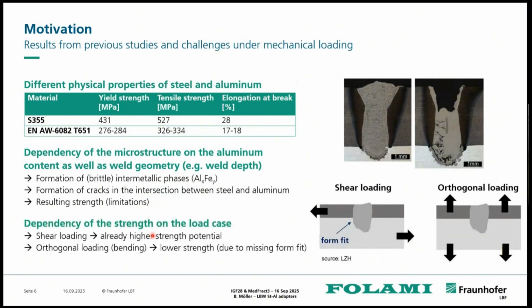And the question is then, what is our loading scenario? In case of such a shear loading, a form fit already exists, so the strength is comparably high, while when we apply such an orthogonal loading, which leads to peel stresses between the sheets and some bending components, the strength is much lower.